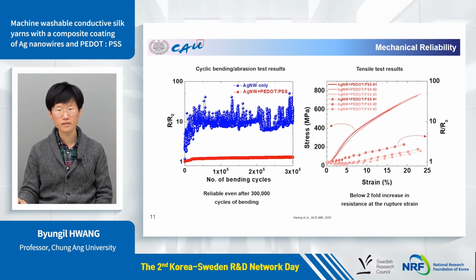This top right image shows the stress strain behavior of our conductive yarns. They showed below two-fold increase in resistance at the rupture strain. And those results show that our fibers also had nice mechanical reliability, as well as keeping the wonderful machine washability.